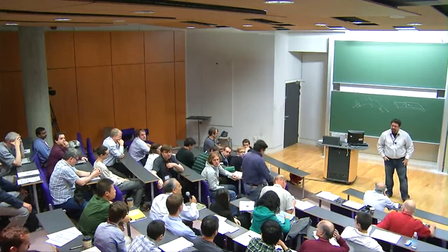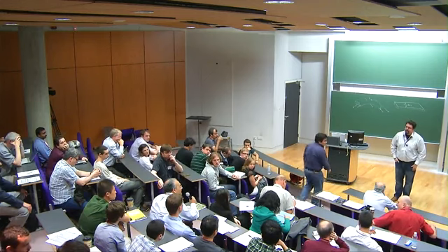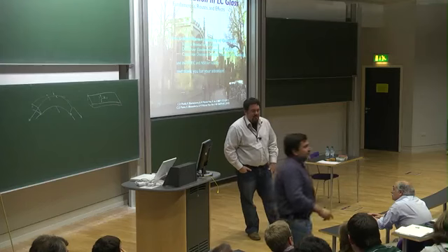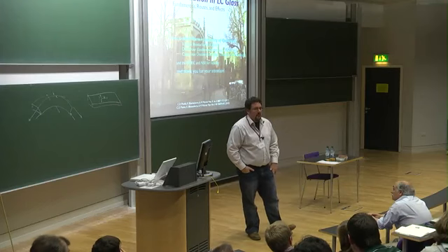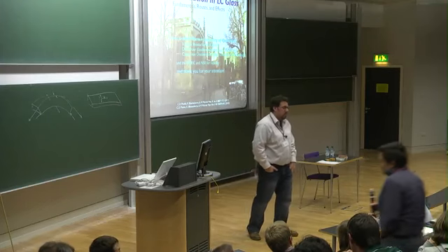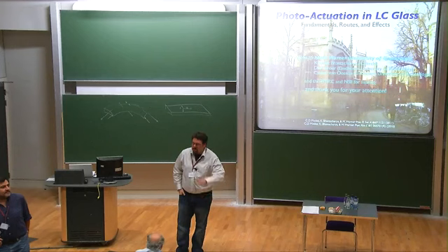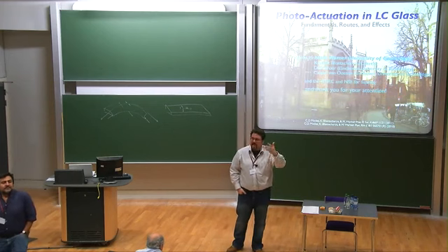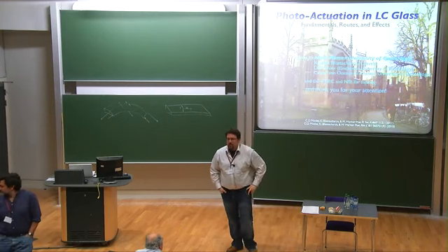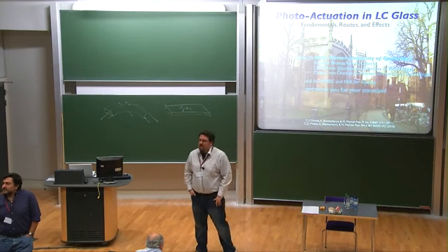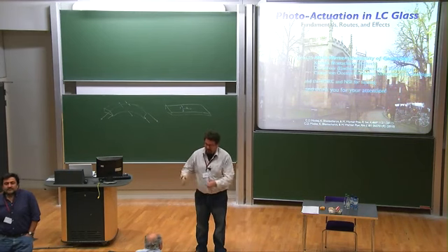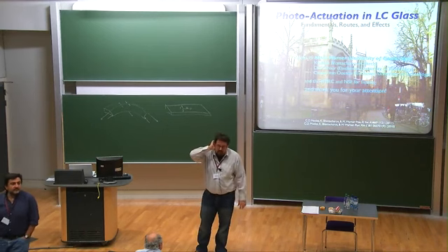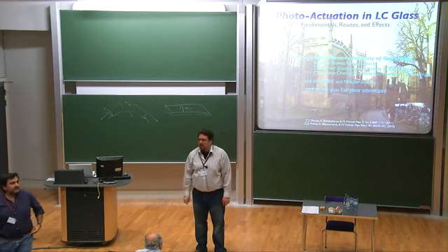Poisson's ratio more than half. Right. So in the glasses, it tends to be from a half up to as much as 2, usually. Usually, you think in rubbers, Poisson's ratio is a half because if it's a half, it's volume conserving. But in a glass, it's just not the case. The Poisson extensions are in some sense stronger. And again, there isn't a complete microscopic theory of what's going on in the nematic glasses.